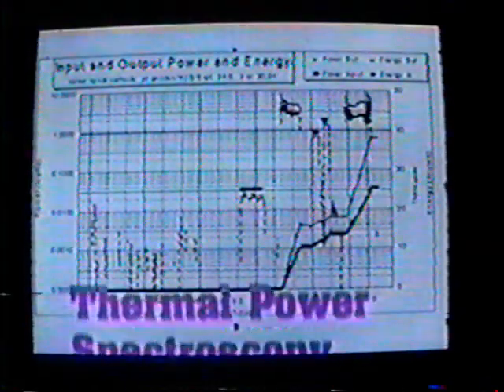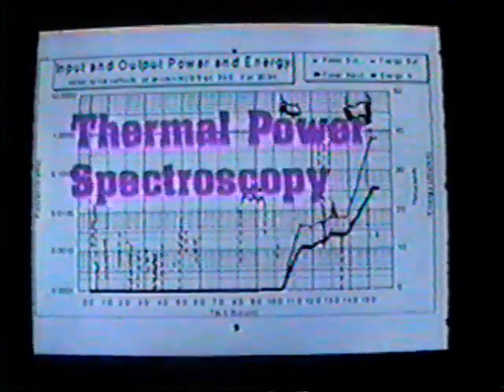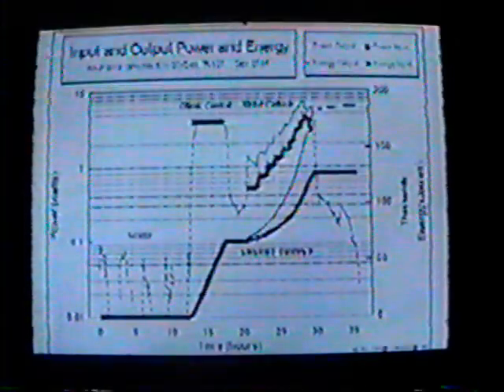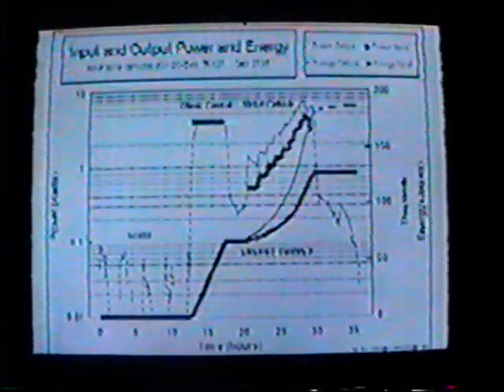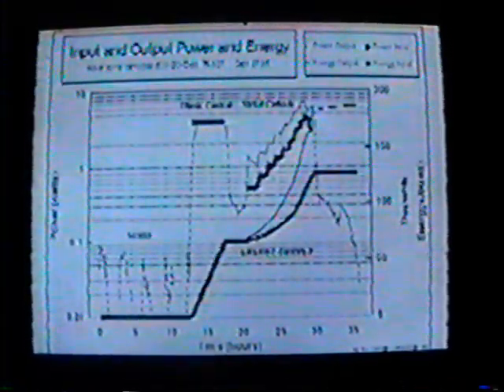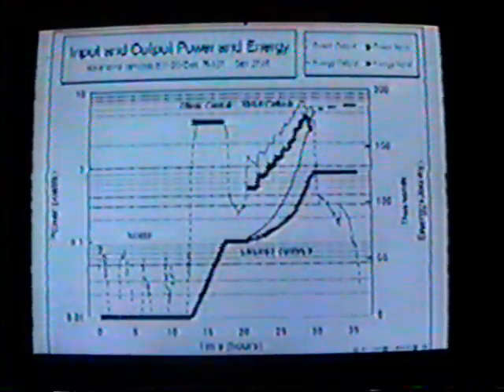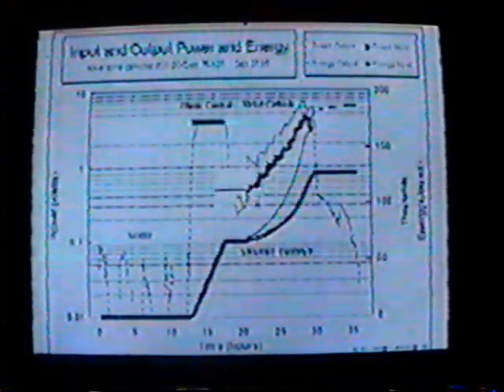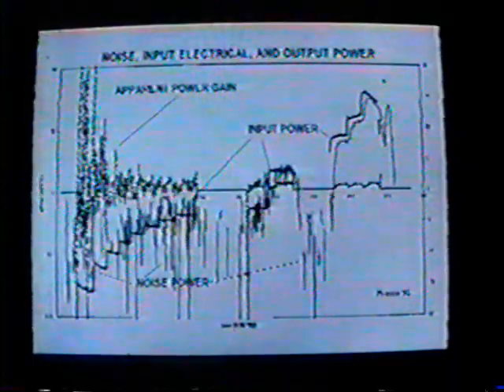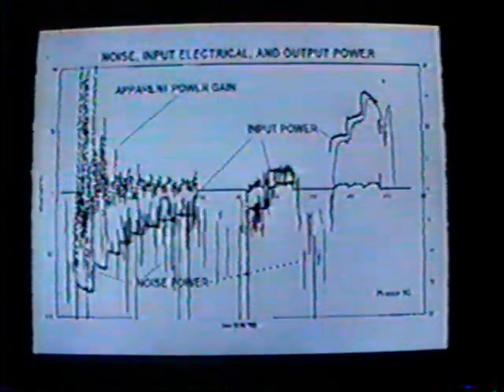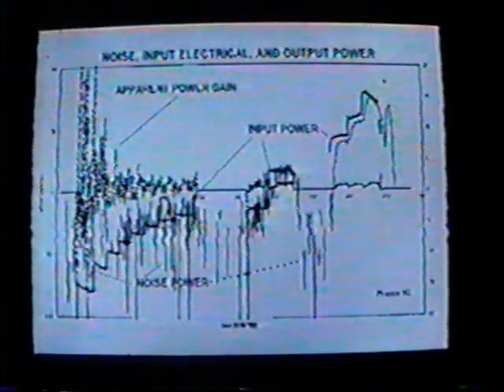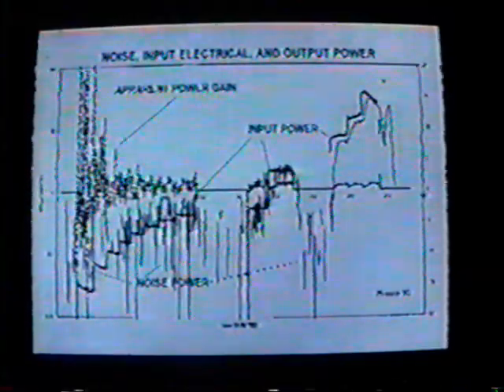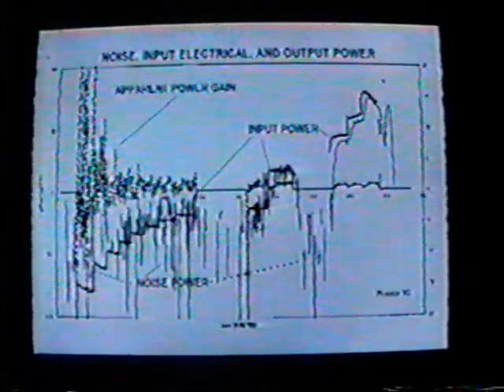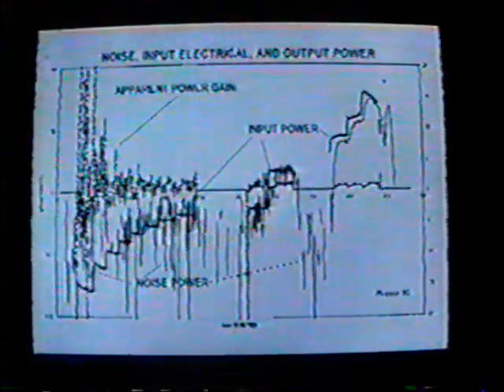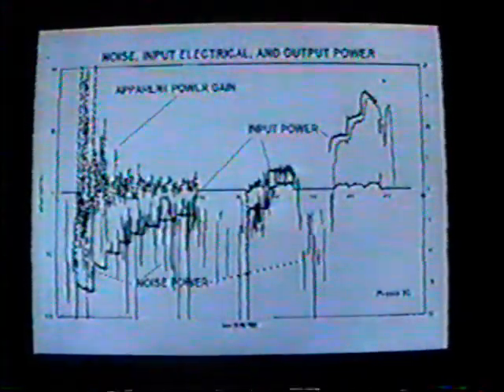The thermal power spectroscopy is based on using V times I as the electrical input power, and this creates a lower limit to the detected calculated heat. One advantage of noise measurement is that false positives can be ruled out when the system is driven by input electrical powers on the order of the noise level, as seen in the case on the left.